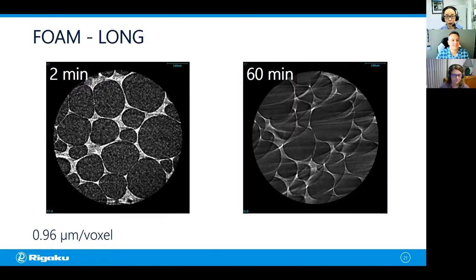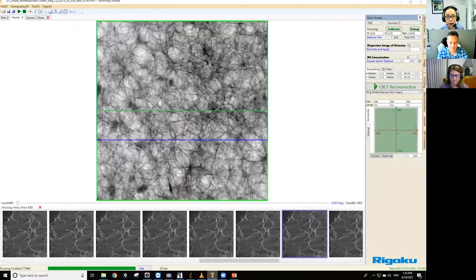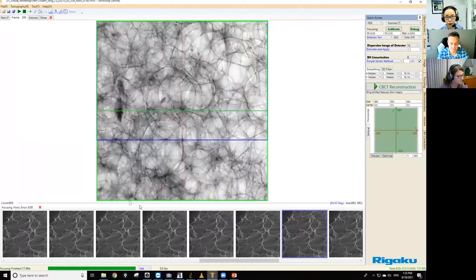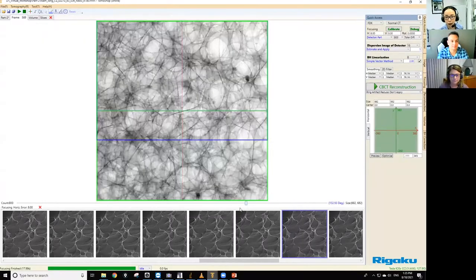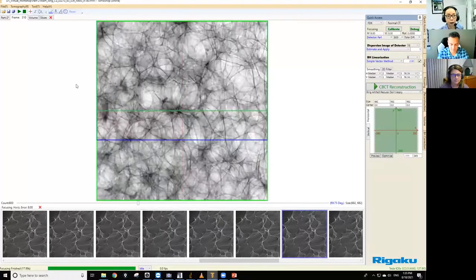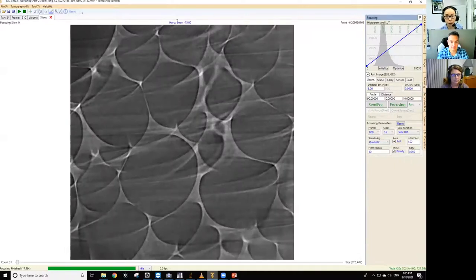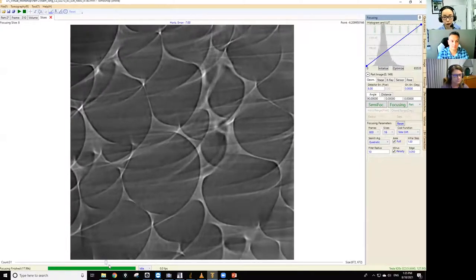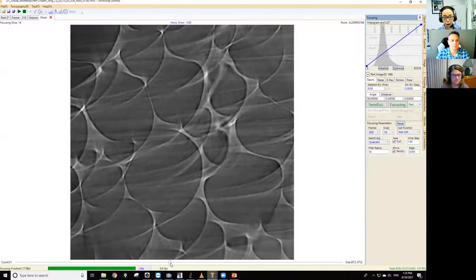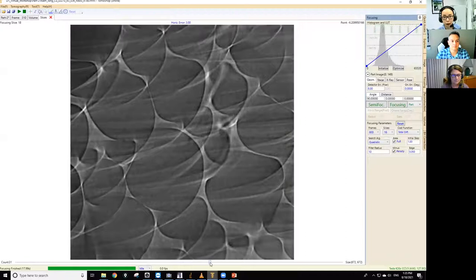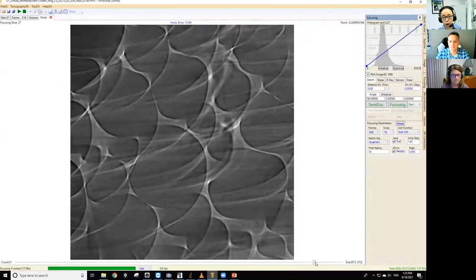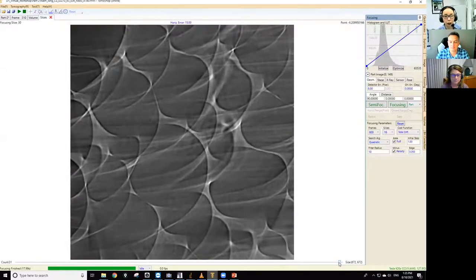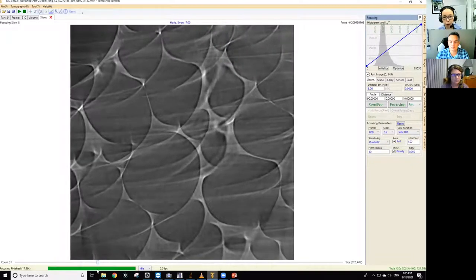So let me switch the screen and show you the center correction. This is the 60 minute scan. You have 800 projections, and when you just look at the projections, you can't necessarily tell that the sample is moving around. But if you look at the focus correction, you see the focus value at the top; zero is the value closest to the mechanical alignment. At minus 15, that's of course out of focus. But when I get closer to zero, I don't see any sign of image focusing. At the center, zero, it doesn't focus, and you can pass it and go all the way to plus 15, but it doesn't focus at all. And this is a really typical sign that the sample was moving during the scan.